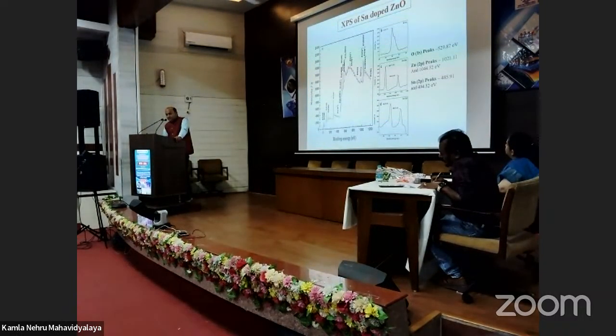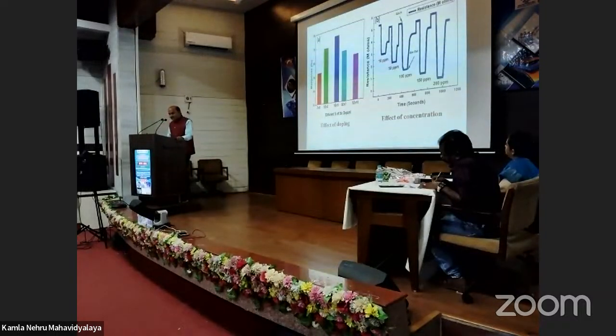XPS we have done. The O 1s peak is observed at 529, that is binding energy 529.87 electron volt. For zinc, there are 2p peaks of orbital form. Sn also has 2 peaks. And this is the study we have done.